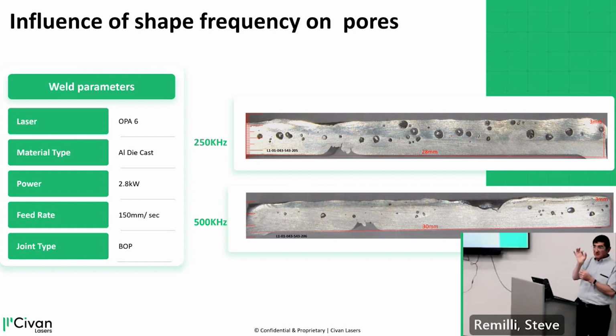Because when you're talking about these scales of tens of microns, and you have temperature gradients going from 2,700 degrees to 20 degrees, these huge temperature gradients at these small scales actually work in nanoseconds. And you can see a clear difference if you're working at 250 kilohertz and 500 kilohertz. In fact, we have a lot of research that we do that even at more than a megahertz, the keyhole and the melt pool feel the difference of these very, very high speeds, which is completely not intuitive, because if you think about heat, you think it takes milliseconds at least for heat to go from place to place, but it's not true when talking about these small scales.